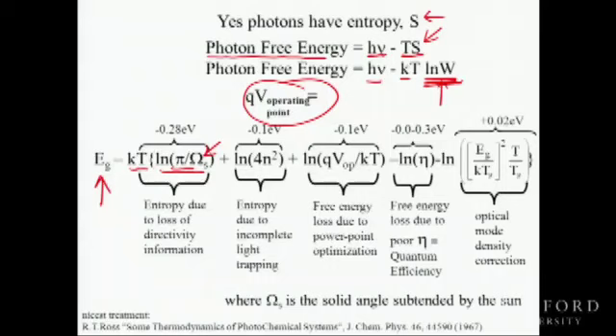Immediately from this kT, in natural log, it's roughly 30,000. Natural log of that ends up being close to 12. And so we lose, let's say, 11, 12 kT. So we lose 280 millivolts immediately. Okay. Let me put some other factors in.